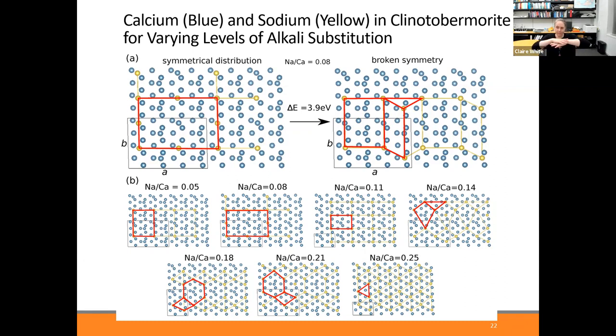So if you think about this interlayer region that we have in these gels, there are calcium atoms in that interlayer region. Do you replace calcium atoms that are in the vicinity of each other, or do you replace calcium atoms as far apart as possible, for example? What we found here is we want to have a symmetric distribution of the calcium atoms to end up with a lower energy structure, meaning that it's more stable. Whereas if a less symmetric replacement is done, we found that the structure is less stable. So it's more stable when the replacement is symmetric, and less stable when the replacement is less symmetric.